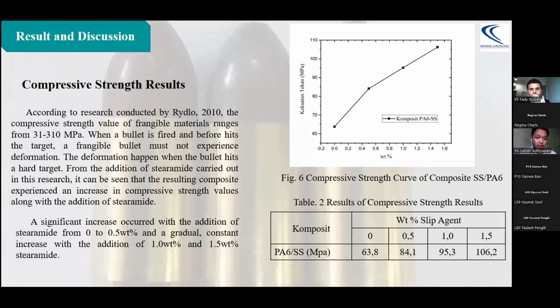And then compressive strength results. According to the research conducted by Rydlo, the compressive strength value of frangible bullet ranges from 31 to 310 MPa. When a bullet is fired and before it hits the target, a frangible bullet must not experience deformation. The deformation happens when the bullet hits a hard target. From the addition of stearamide carried out in this research, it can be seen that the resulting composite experiences an increase in compressive strength value along with the addition of stearamide. A significant increase occurred with the addition of stearamide from 0 to 0.5 weight percent, and a gradual constant increase with the addition of 1 to 1.5 stearamide percent.